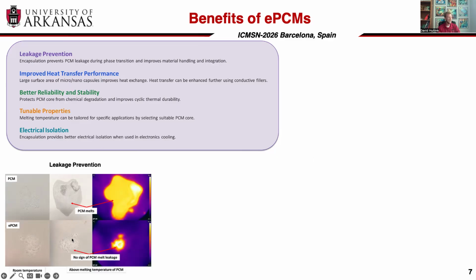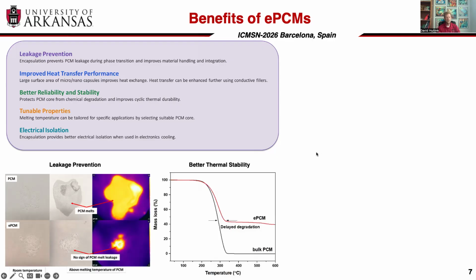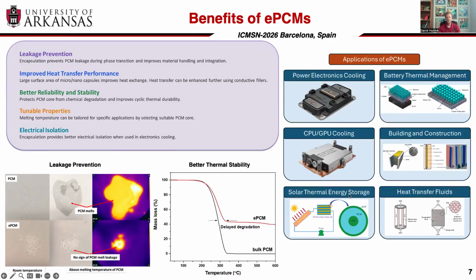In the case of the ePCMs, it looks like a white powder here. That's just the particles. And above the melting point, we notice that there's no observable morphological change or leakage event, but yet we're still seeing the thermally active event. But we're also seeing that that shell improves the stability of the organic material on the inside. When we do TGA testing, we see a slight delay of the degradation of the interior PCM because we've now basically encased it in the shell, which makes opportunities for integration in electronic systems even better.